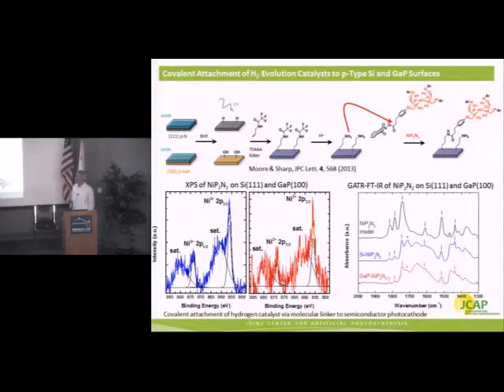Likewise, we've done FTIR spectroscopy. This shows us that the ligand environment of that catalyst, once it's immobilized on the surface, is similar to the catalyst in its as-synthesized form. Okay, so these spectroscopic measurements verify that we've synthesized what we aimed to.